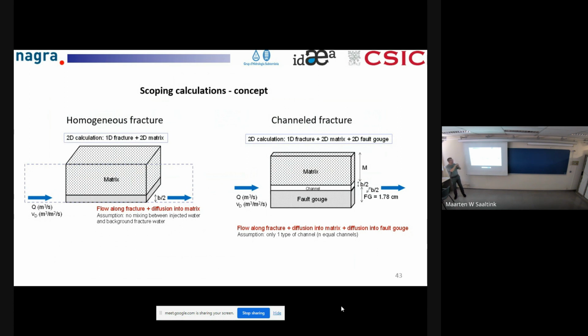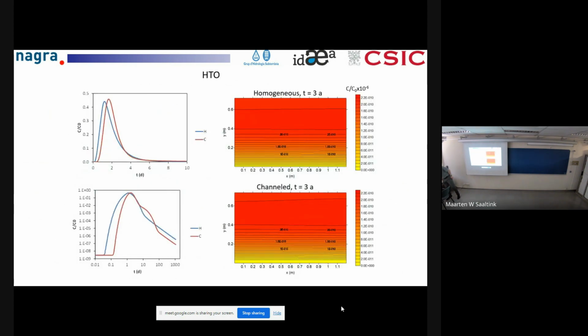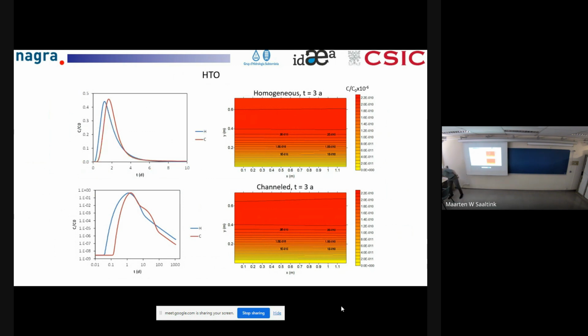Again, the point here was just to see what we can expect from the results, rather than to make a really accurate calculation. In any case, we compared with the experimental result from 1999 with the same conditions, and actually the measurement is this second red curve that you see.